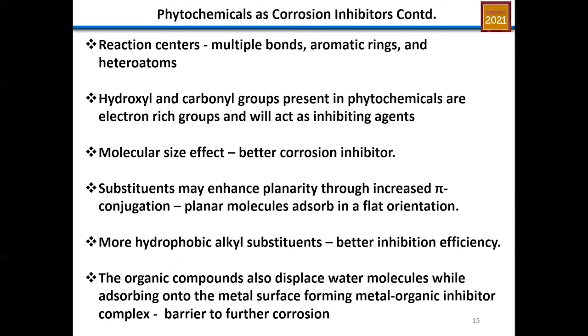You also have an influence from the molecular size effects. Most of the phytochemicals are large-sized, and this will provide better corrosion inhibition. The substituents may also enhance planarity through increased pi conjugation. It's known that planar molecules will adsorb in a flat orientation. In that flat orientation, they will cover a reasonable area of the substrate surface. And the more hydrophobic alkyl substituents you have, the better inhibition efficiency you could also get.